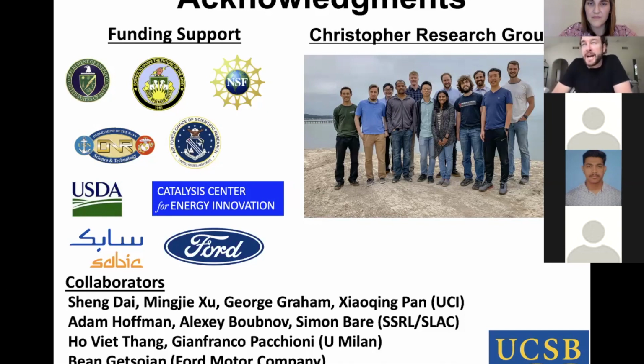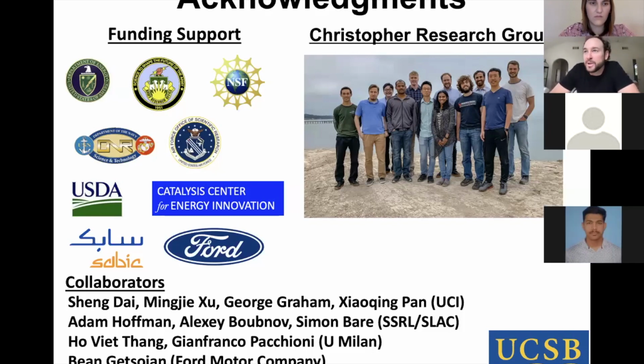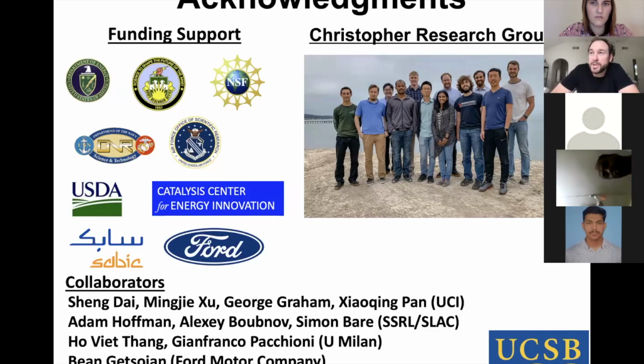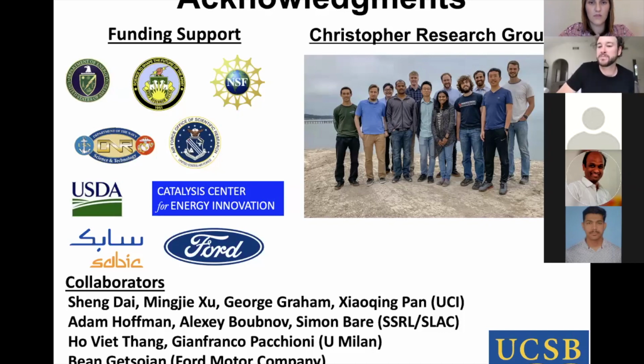Yeah, so I assume this was relating to the rhodium on TiO2 work. That was really just some initial work. That was the first paper we wrote on it. But since then, we went further, and we found that if you go down below about 0.1% of rhodium on most supports that are high surface area, we're typically working on 150 to 200 meters squared per gram surface area, and importantly, you don't reduce this in hydrogen above 200 or 300 degrees Celsius, then you get mostly single atoms. It's not perfect, but along that direction.